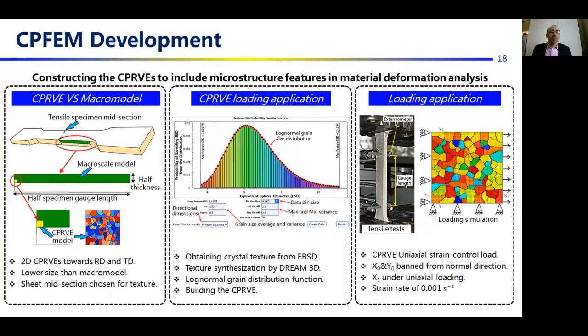For CPFEM development, 2D CPRVEs are developed for the rolling and transverse directions, and the material microstructure is synthesized by the DREAM 3D software into the CPFEM model, and loading is applied by strain-controlled loading on the CPRVE models to simulate the tensile test.